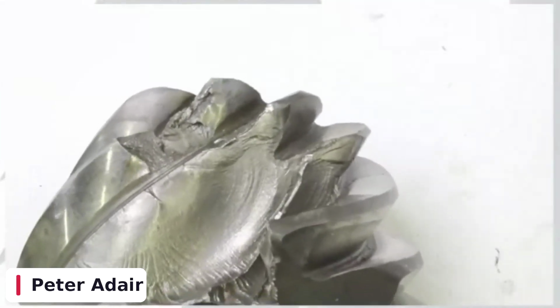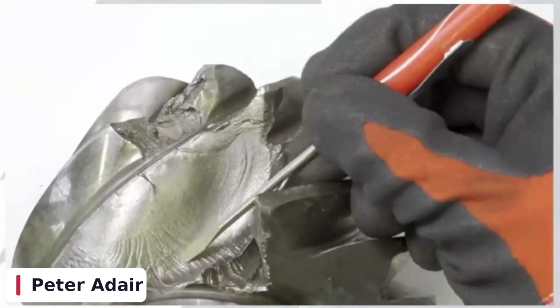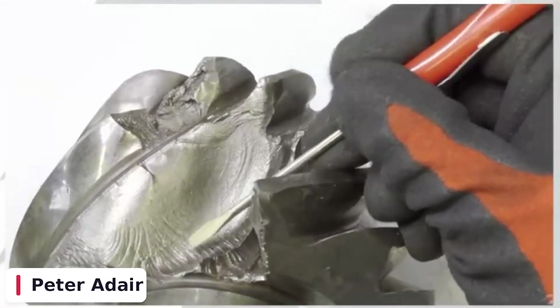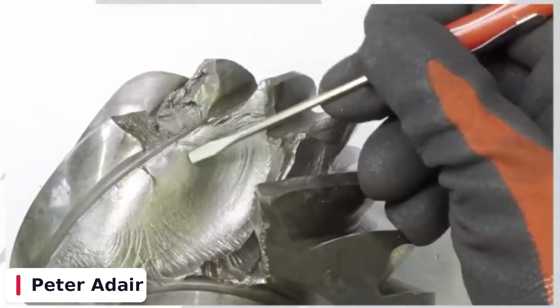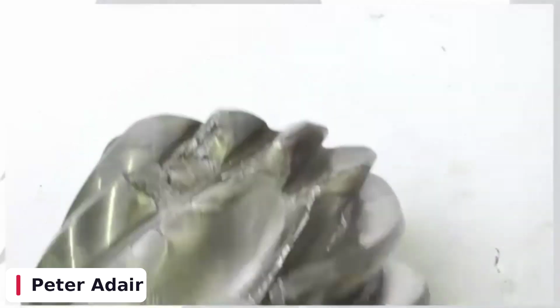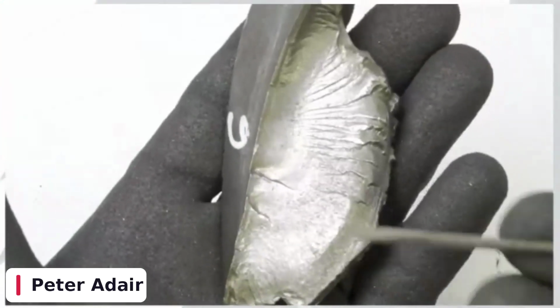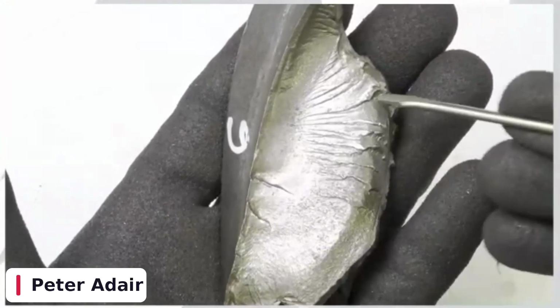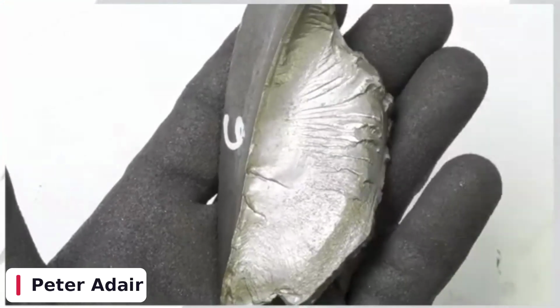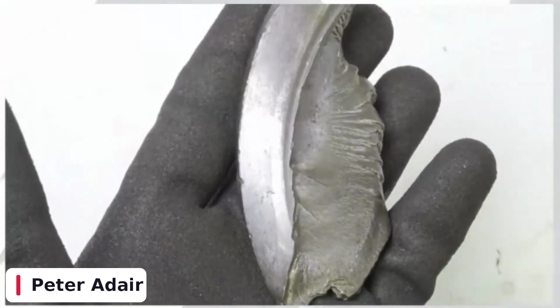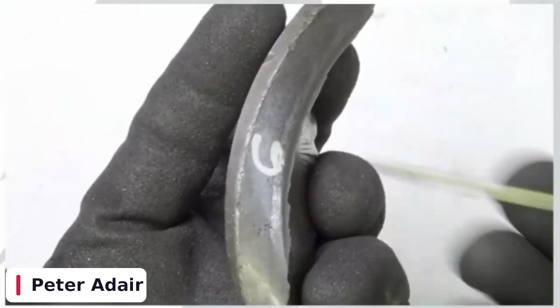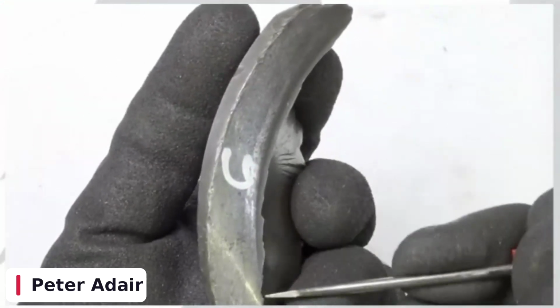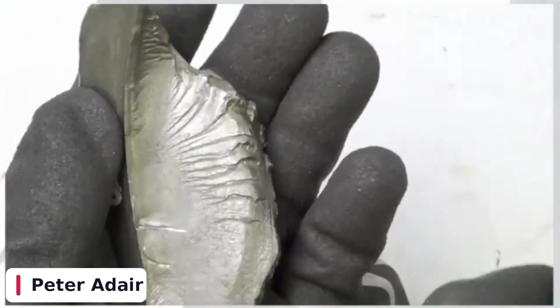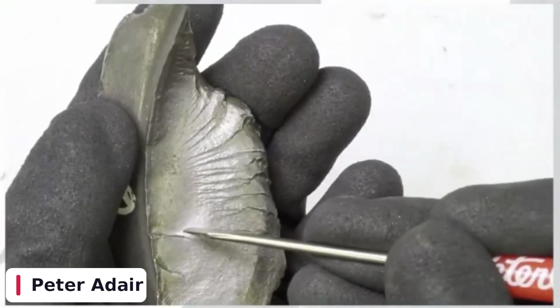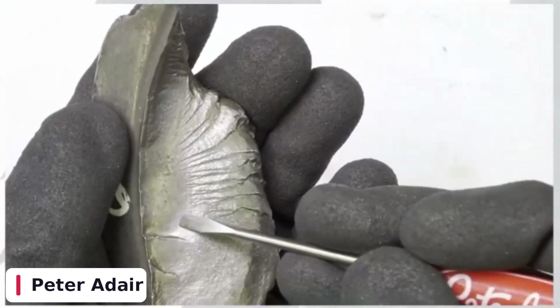So if we look at our chevrons, our mountain peaks here, right? They all point back to here, to here, to here, to here, to here. And if I look at my gear tooth here, right? I have an origin, an origin, an origin. All my chevrons are pointing back to these origins. On a curved part, like we're seeing here, because this is curved, we're going to have multiple cracks and multiple starts of those cracks. So you can see slightly right here through the middle, you can see those beach marks or those swirls or those ripples.